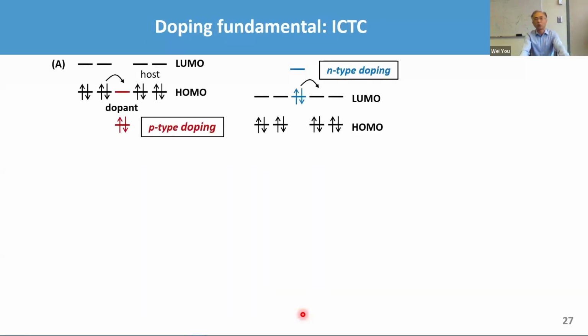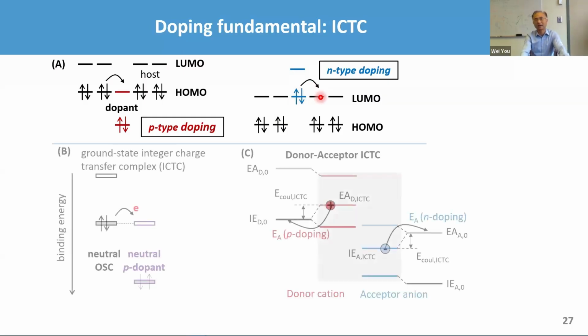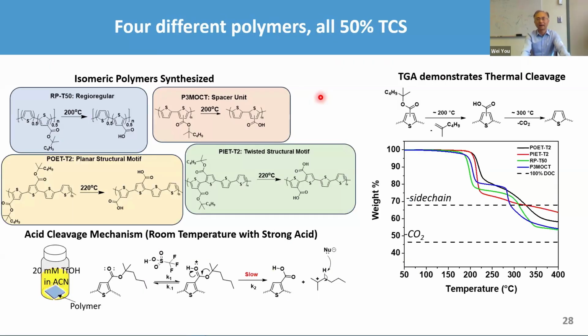Okay. So doping is very simple. For the chemistry people, we are talking about redox chemistry. If you have a dopant, p-type doping means that you essentially have a dopant that's going to take an electron away from your polymer. If you have n-type, you have a dopant pumping electrons into the LUMO of your conjugated polymer, you have n-type doping. So that's about it. And the rest of them, don't worry about that. So in this particular case, we were hoping to understand what's going on with this. Can we use the so-called cleavable side chain polymer to get higher conductivity?